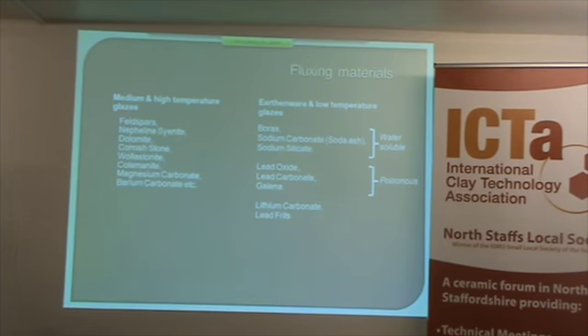But if you've got something which is dissolved in the water, then it would be taken right with the water stream into the inside of the pot, and when you put the pot down and the pot dries out and the water evaporates away, it brings with it the dissolved salts that have gone into the structure and deposits them on the outside of the glaze. So they effectively unmix themselves.